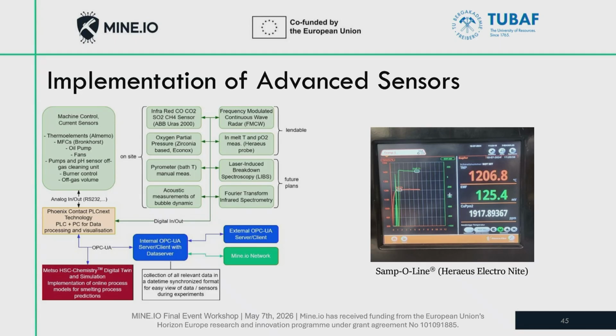We used, for example, the Heraeus Electro-Nite probe to detect PO2 inside of the slag and the copper, which also gets us a direct temperature measurement. This is not a continuous process, but a dip measurement, but a very important one to get the temperature of the melt and the PO2 to drive it safely and to know where we are in the process.